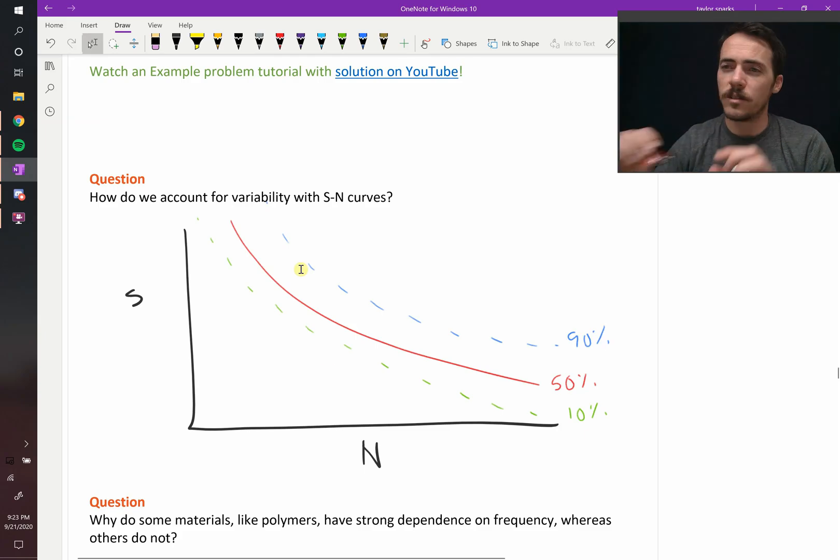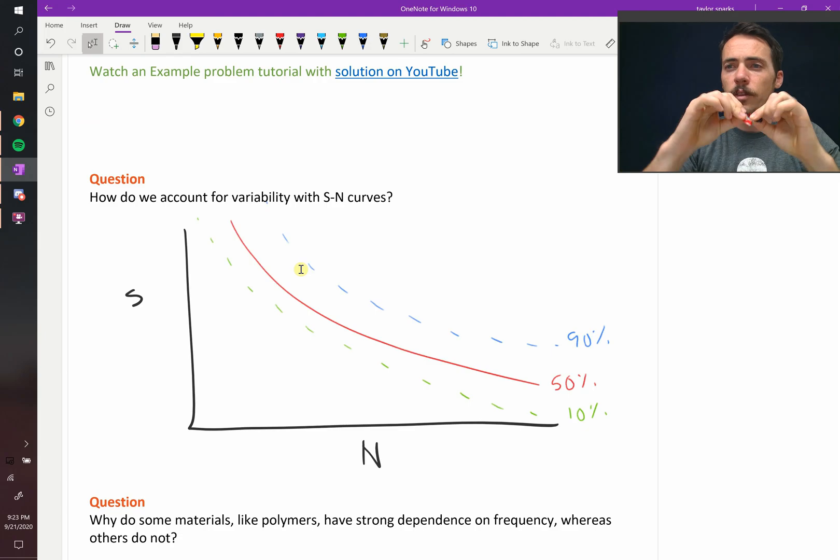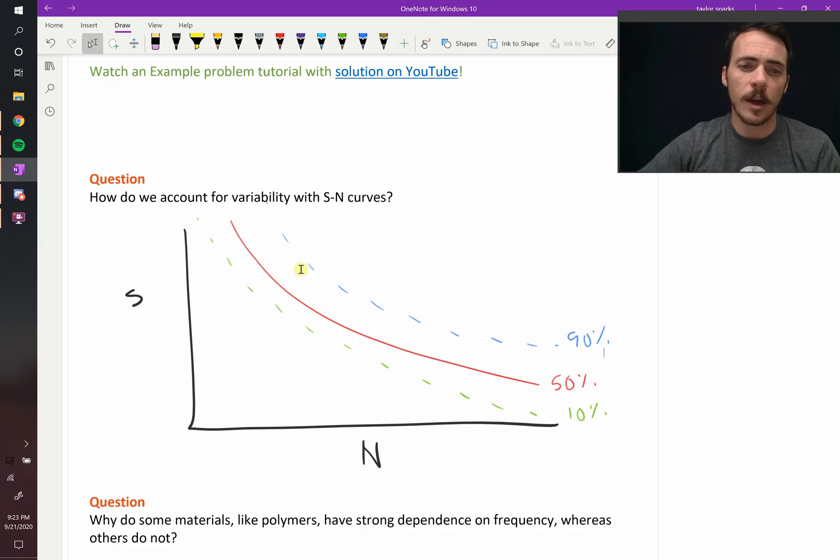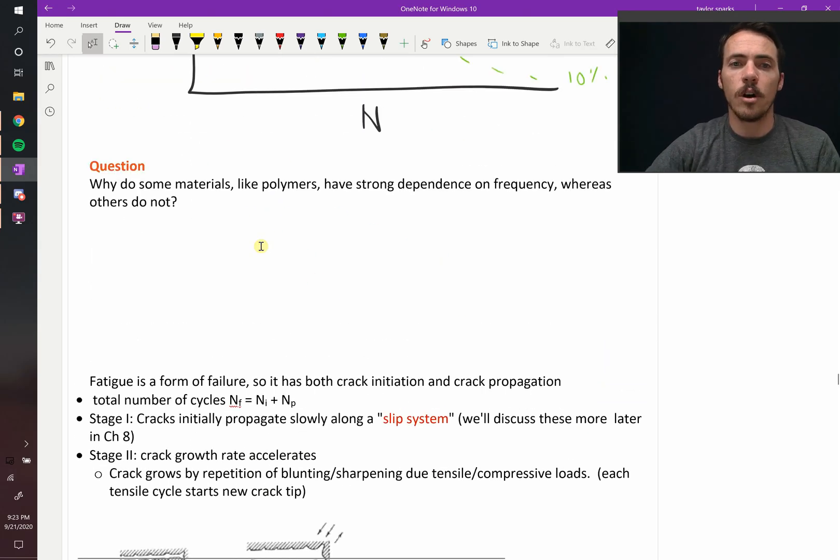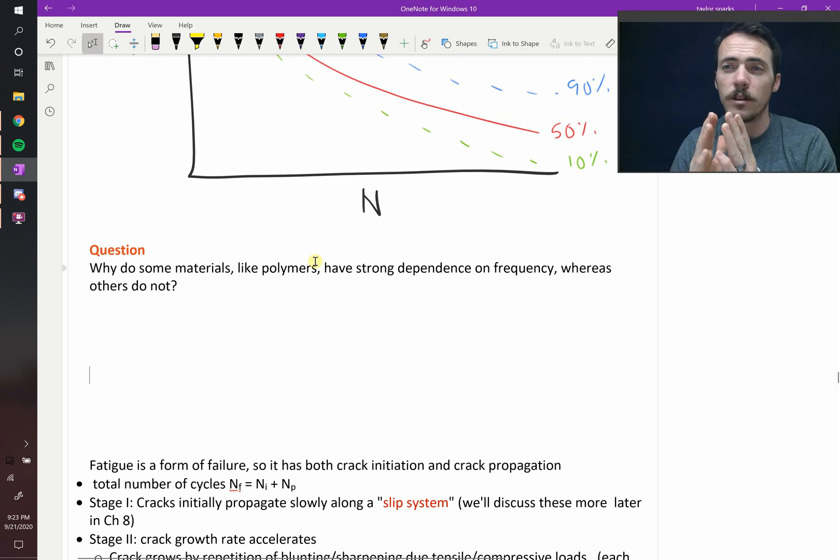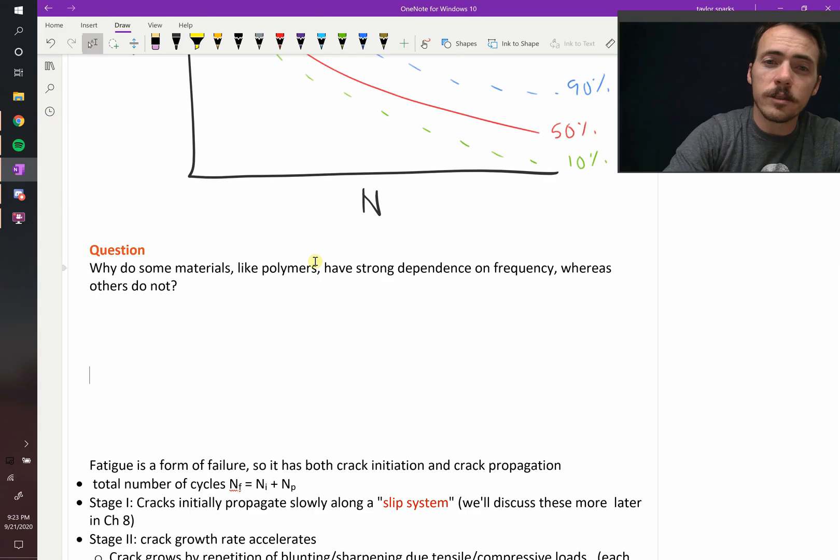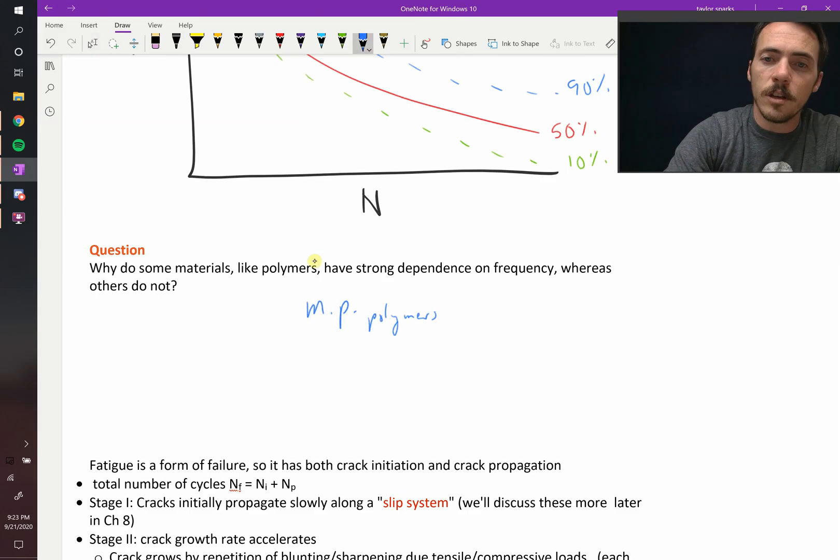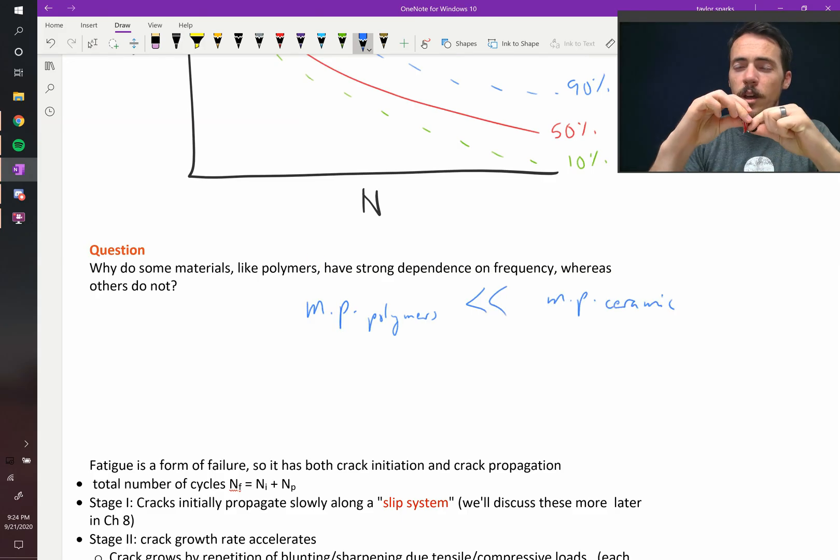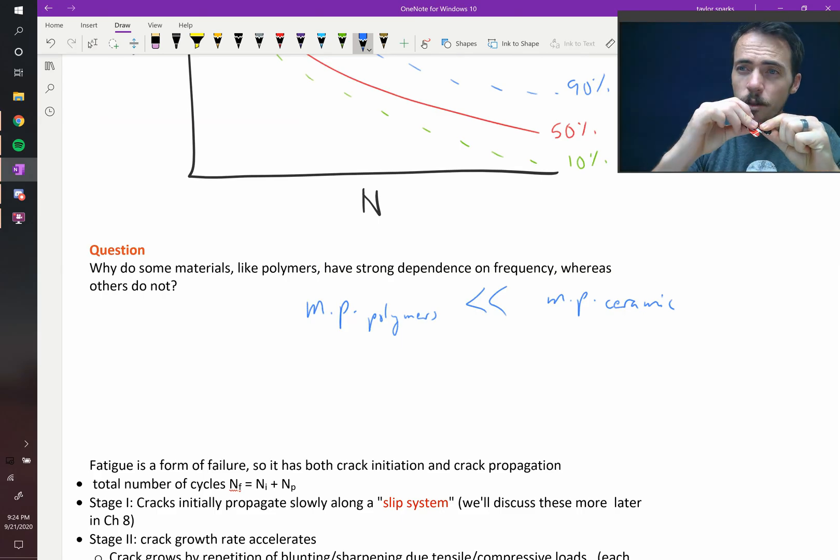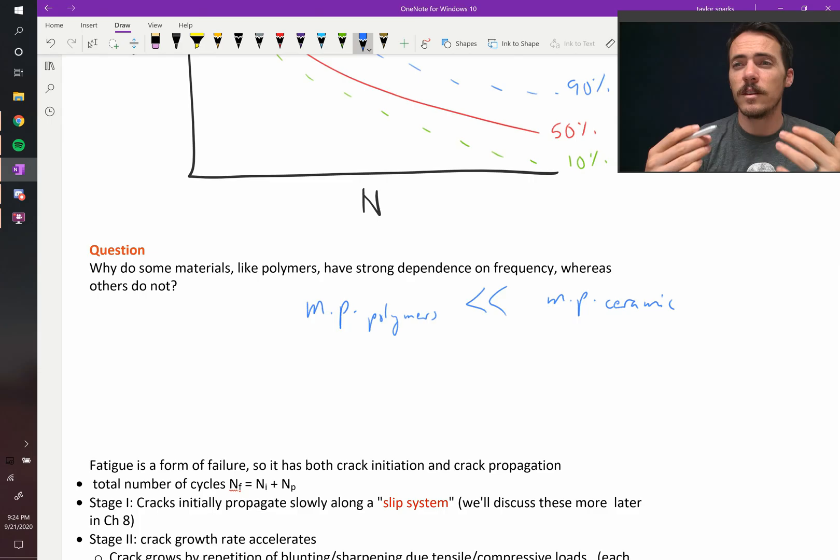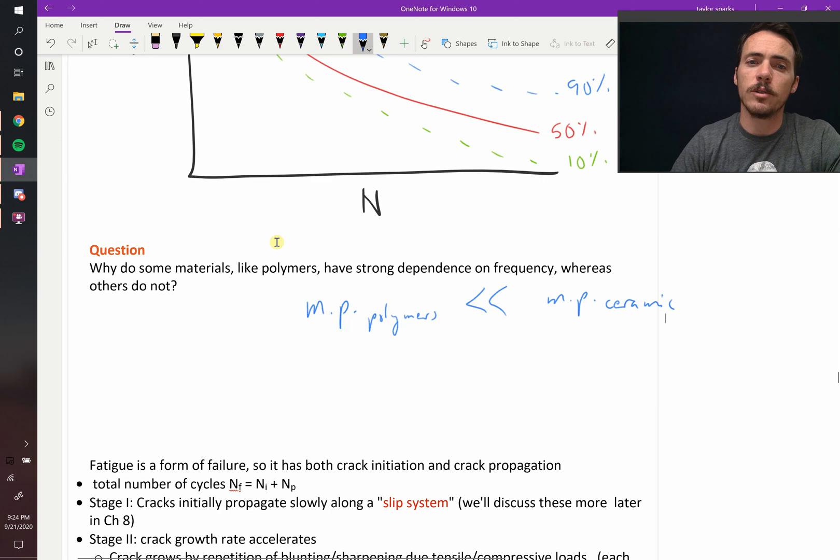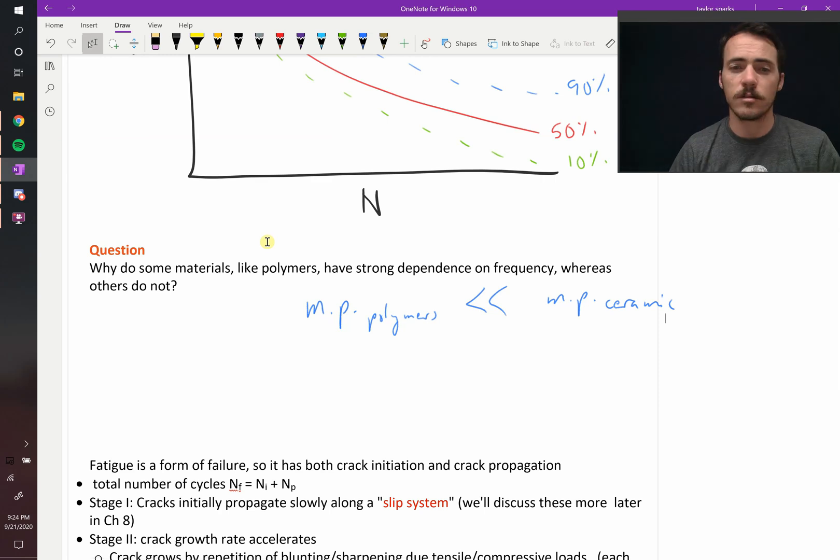Now when we do this testing, cyclic testing, we're bending back and forth, we find that some materials have a real temperature dependence or a frequency dependence and others don't. So why might that be the case? For example, polymers tend to have a really strong frequency dependence. If you cycle them really fast, they're weaker than if you cycle them slowly. So what happens is, remember, polymers have a low melting point. The melting point of polymers is much lower than something like a ceramic. And as you bend these things and cycle them, loading and unloading them, you're generating a little bit of heat. And so if you're doing this really quickly, you're generating a lot of heat. So you can actually heat these things up. And so the chains become more mobile, and then they start deforming, and eventually you get crack formation. So that's why you get temperature dependence more severely in polymers and then in metals and finally in ceramics.